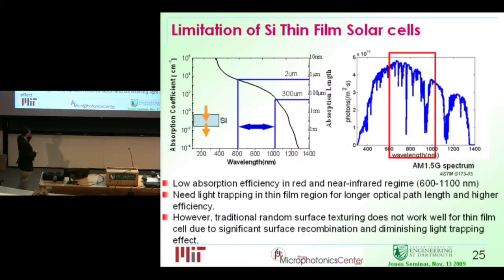However, there are limitations of thin film solar cells. Not only silicon, but other thin film solar cells. But silicon is a good example. For example, because of the absorption coefficient roll-off beyond 600 nanometers, you find the absorption length will increase from 2 microns to 300 microns. So if you just absorb things with a very thin layer, you lose a lot of the solar spectrum, a lot of solar energy. So what can you do to fix this problem?